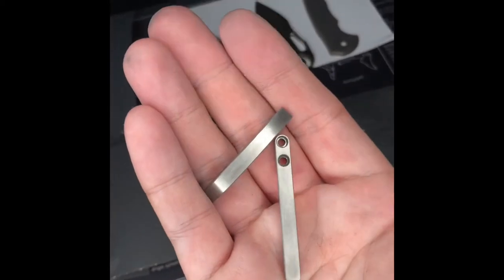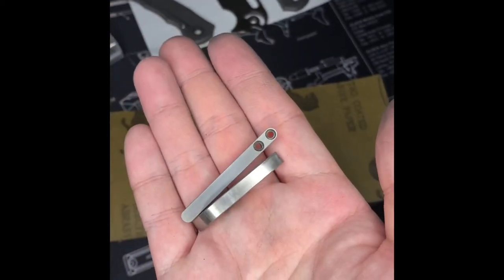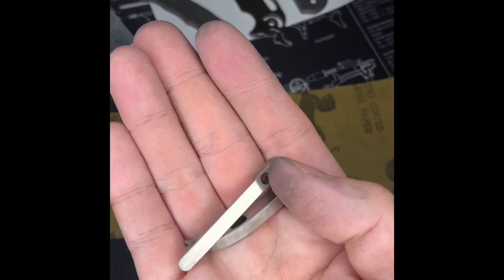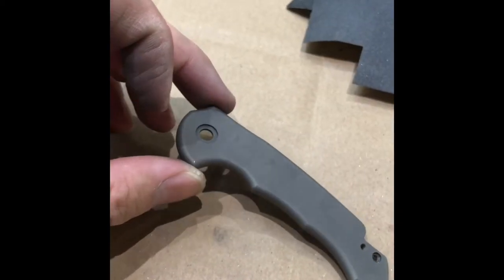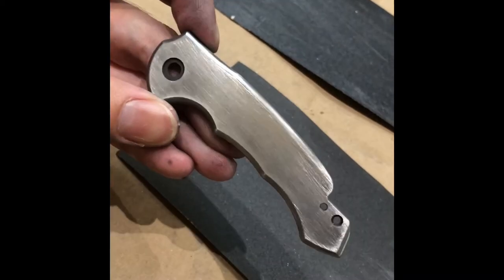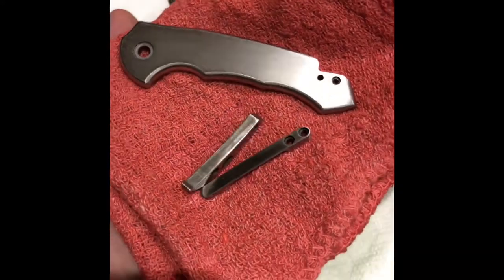Here we have 800, then 1500 or 1200, and now just finished 2000. This is what it looks like after sanding — I think I spent about three to five minutes on each grit. They're looking really good — you can barely see the lines now. Here we have the show side starting on 150 grit, moving to 320. Just finished with 320. And here it is after 800, 1500, and 2000 grit — and now I'm going to start polishing.